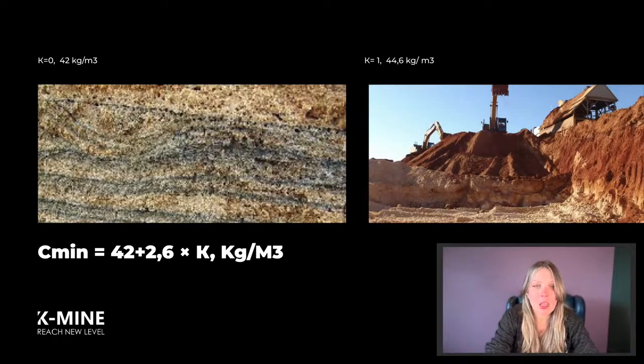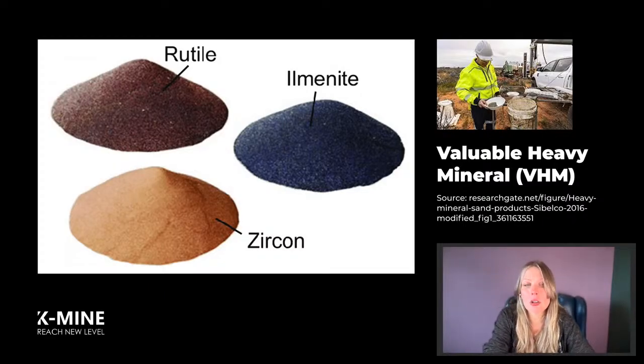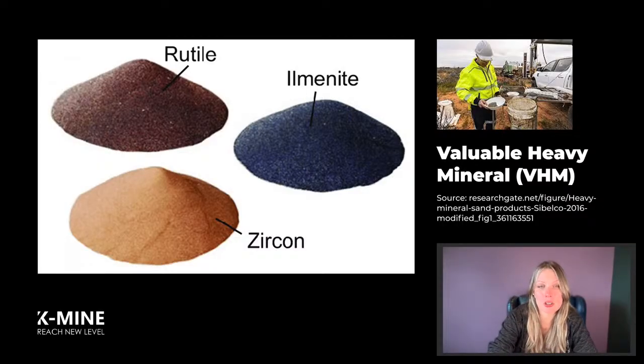So one of the biggest challenges in resource estimation for mineral sands is getting an accurate breakdown of minerals like ilmenite, rutile, zircon, leucoxene, because the production cost can vary dramatically depending on which mineral dominates. Ilmenite is usually the most abundant titanium mineral in heavy mineral sand deposits. Its theoretical titanium dioxide content is about 53%, but interlayering and weathering can change this significantly.